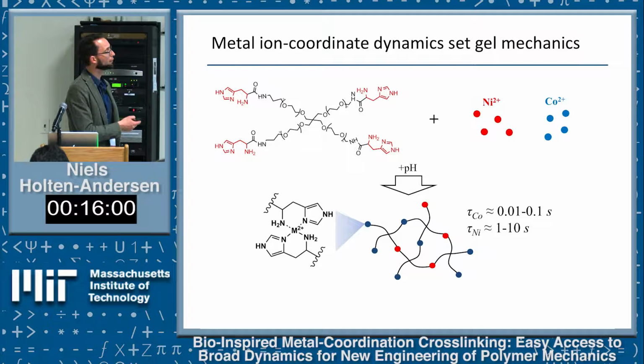Again, we use this 4-arm polymer. We use a slightly different ligand than the one I showed you before. This type of ligand is called histidine, to bind divalent transition metal ions, but we have a lot of choice in terms of what ligands and metal ions we use. Again, from the literature, we knew that the nickel metal ion should give you long-lived crosslinks on the order of tens of seconds. The cobalt ion should give you something much shorter-lived and much more fluid-like.